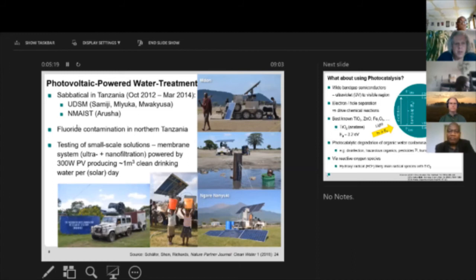engineering-oriented field research. We were looking at fluoride removal, which is a common contaminant in the northern Tanzanian region. And if you look at this system shown on the right, you see a trailer-based system. It has 300 watts of photovoltaic panels, and it's equipped with two membranes, an ultrafiltration and a nanofiltration membrane. And it's simply the photovoltaics directly powering the pump can produce about 1 m3 of clean drinking water per day, or I should say per solar day.